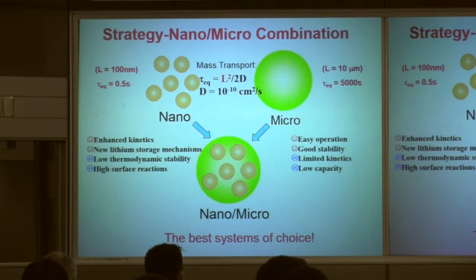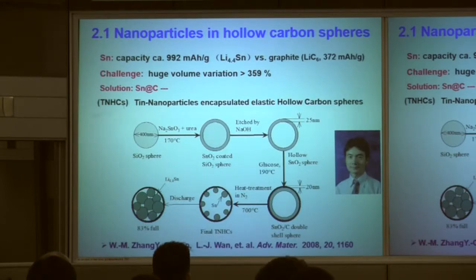not stable. But if you combine this one and the microstructure together, if you can prepare the nano and microstructure and make these two structures together, you can get a new structure. The structure will be very good for the electrode material application. For example, we prepared nanoparticles in the hollow carbon sphere. You see, first like tin.